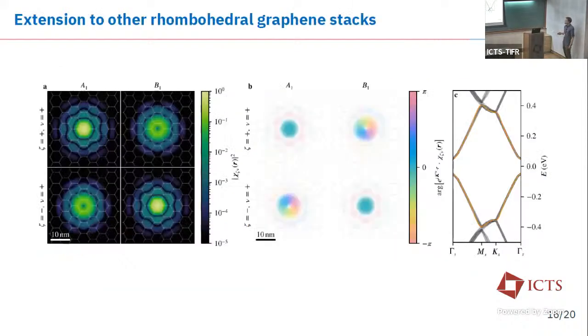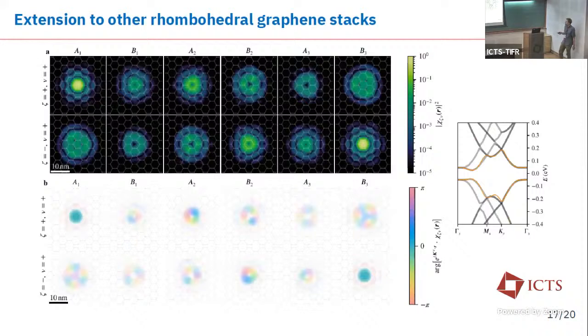Okay, having all of this together for the Bernal bilayer graphene, we can seek for extensions to other rhombohedral graphene stacks, and I'm just going to quickly showcase them, just with the reasoning that we know it works also for the other systems. So for monolayer graphene, we can write down those exponentially localized Wannier functions in the same way. We get the phase winding, as I discussed before, with 0 and 1, and we perfectly reproduce the parts of the band structure that are close to 0 energy. Also for rhombohedral trilayer graphene, same story.